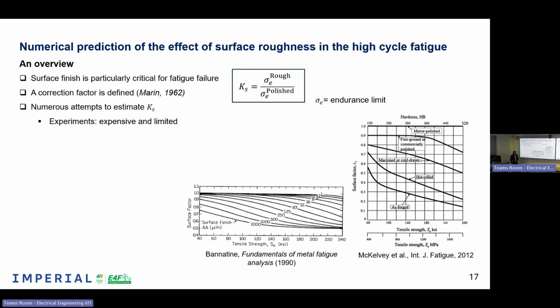The problem of experiments is that they are expensive and they are also limited. To do a fatigue curve in this kind of area, we need about 10, 12 specimens. This is at least what regulations say. If we need to include the effect of surface roughness, then maybe we need more because surface roughness is a random phenomenon. So we need to try several times in order to get a good, reliable value. So we need to spend a lot of money buying specimens and breaking them to build just one curve.